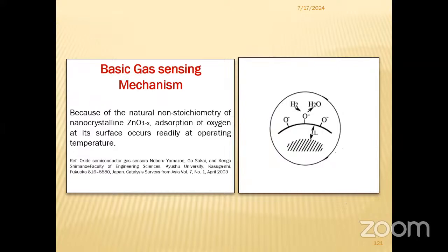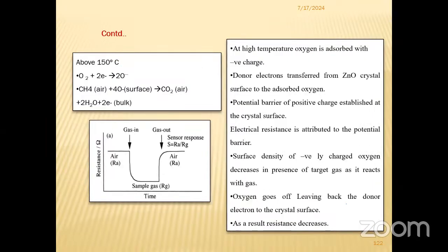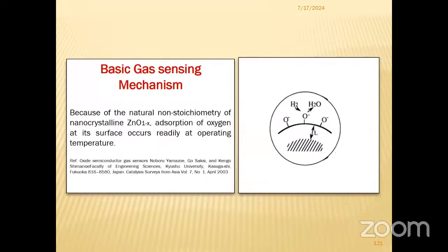When oxygen makes a poor bond with the surface atoms of the sensing layer, oxygen accepts electrons from the gas sensor sensing layer surface. That's why it becomes O minus, and the sensing layer surface becomes positive. Thus we can see the poor bond has been established. This bond is called a dangling bond. So the sensing layer surface is the donor and the oxygen atom is the acceptor. This is the donor acceptor relation. As the sensing layer surface is donating electrons, fewer electrons means resistance is more.